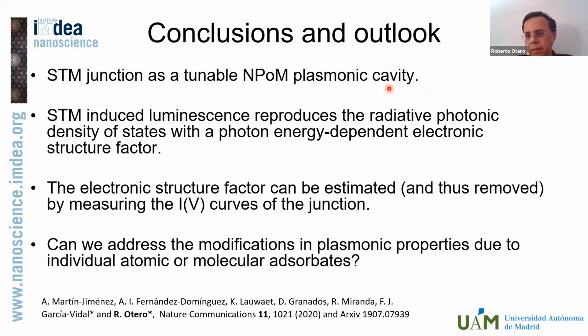Absolutely. That's actually a very good point. What we believe is that we are pretty much at the edge of how plausible it is to apply this kind of theory. According to our measurements, we are at about 1 nanometer. According to the calculations, we observe things that don't make sense and probably reflect non-local effects due to the fact that we are not using the proper theory at about 0.5 nanometer or something like that and below. So we believe that we are very much at the edge. If we push our tip a little bit further, we should be able to observe these effects, which on the other hand would be interesting from the fundamental point of view anyway.